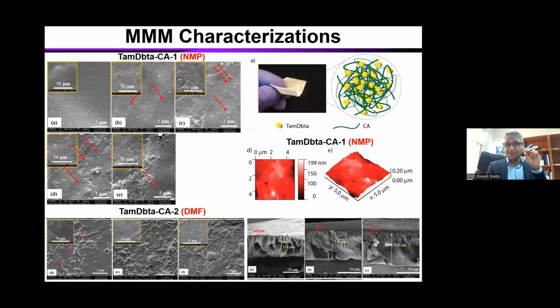The region-specific aggregation started. That's what you can see. But on the other hand, when we use DMF, because the dispersibility is not that great for the COF, we end up getting a kind of agglomeration. Still, we were able to get the membrane. But then we also did the cross-sectional analysis to understand, because when we have this kind of hydrophobic pillars within, then when we do the phase inversion method, it is disturbing the flow of the solvent, right? And because of that, it is creating pores within this membrane. We have mesopores and different size pores within this membrane.